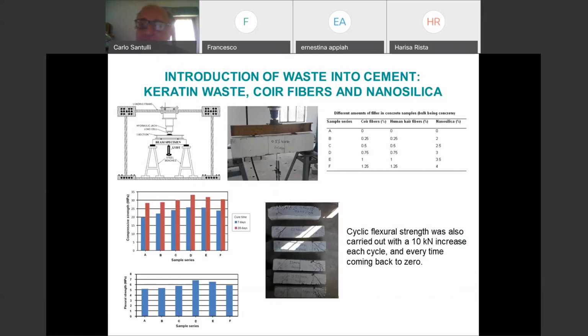And then it compares the different sample series, with different amounts of coir fibers and human hair, small amounts, because of course you start very cautiously with waste, but the idea is to put as much waste as possible. Then they have done some cyclic flexural strength tests. Here are the broken samples, the broken beams. So basically it's a beam, whilst for the compression strength, you may easily imagine it was a cube, more than a cylinder, because these were quite high thicknesses.